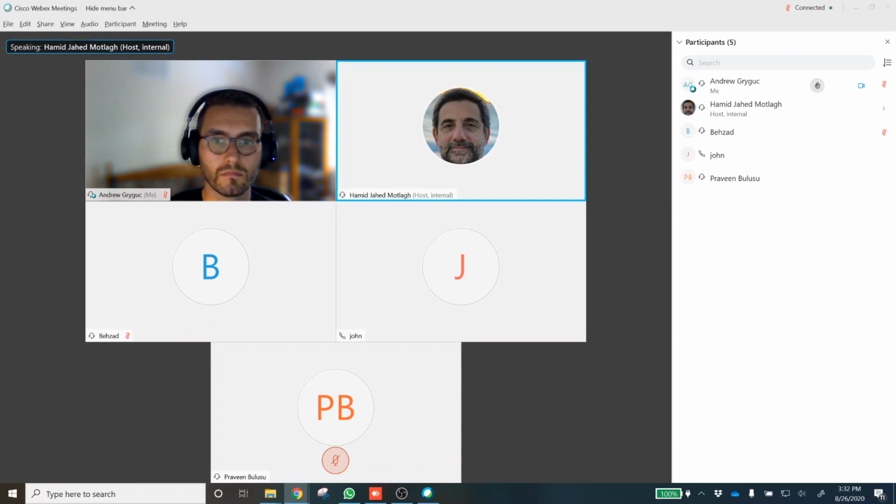Because of that difference in properties, you will get an interaction between the two to generate some internal stresses, which for fatigue is very important. I don't think they would play a big role in static loading, but for fatigue, it does.